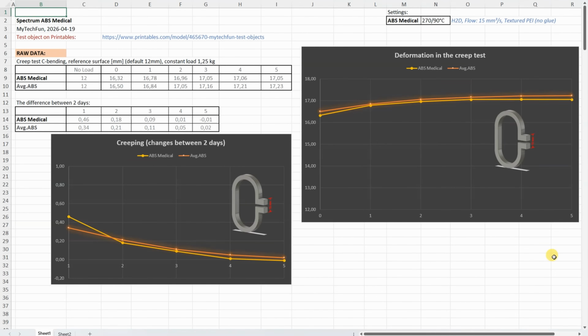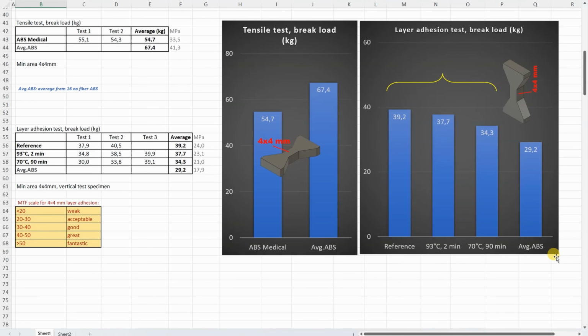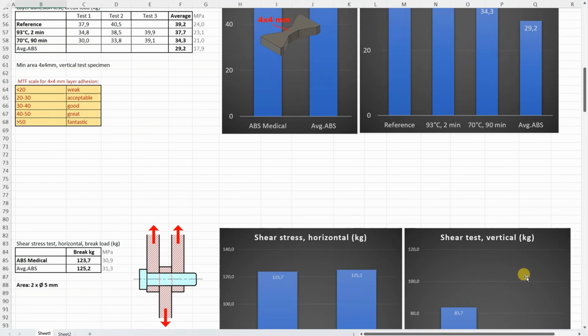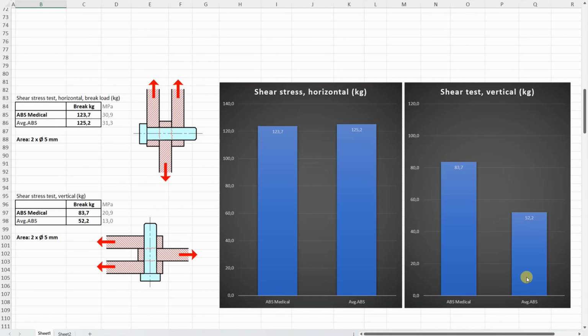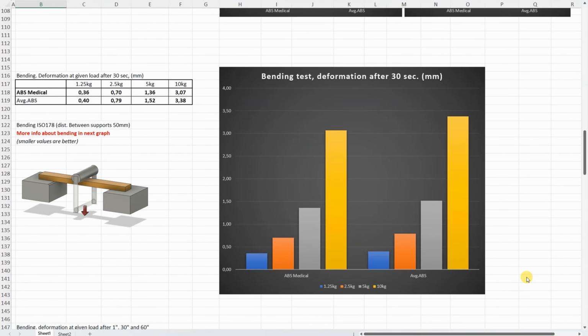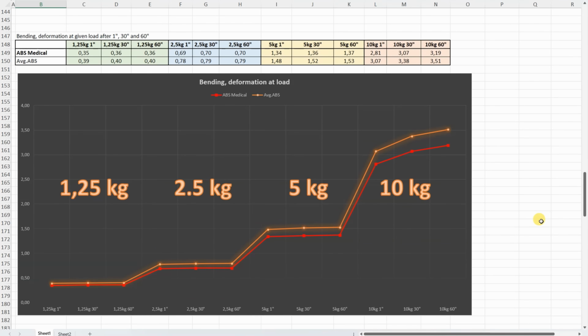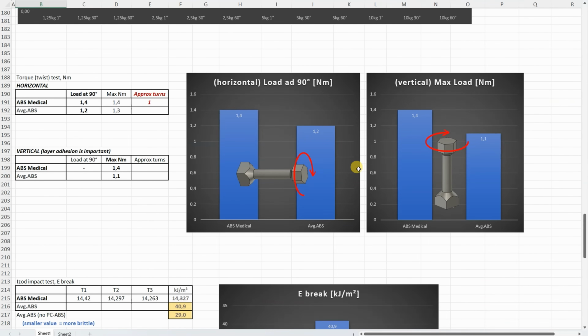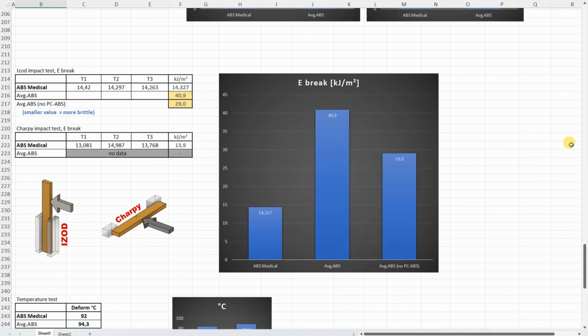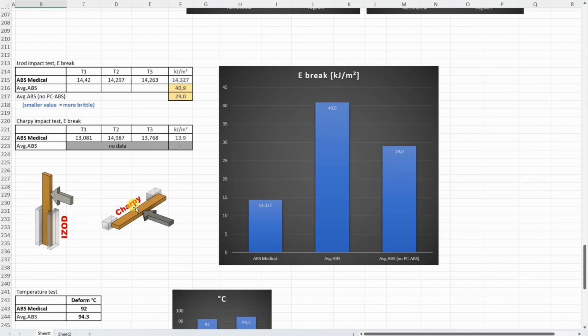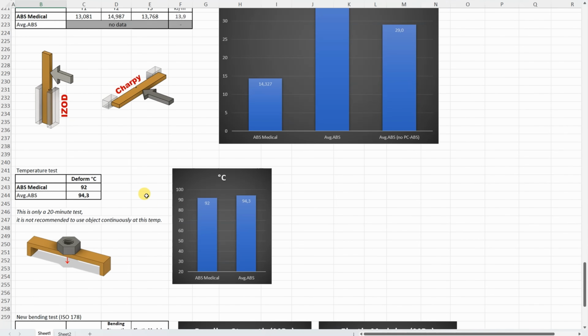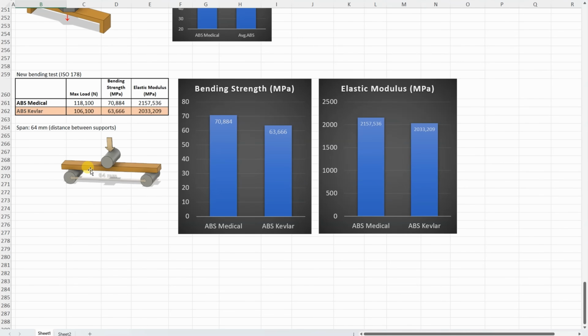Our results one more time. Creep test, tensile test and the layer adhesion with some cleaning methods. Shear test, horizontal and vertical. Bending test, the deformation after 30 seconds. Bending test, deformation under these loads after 1, 30 and 60 seconds. Torsion test, horizontal and vertical. Impact test, Izod and Charpy. Temperature test. And that new bending test.